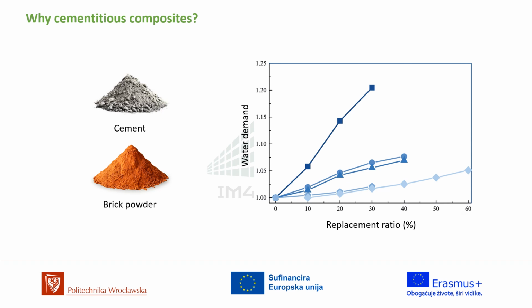Starting with cement. Of course, each of these materials can be replaced. However, incorporating recycled ceramic introduces specific physical challenges that must be carefully managed. As you can see from our experimental data gathered from the literature, crushed brick has a porous structure which significantly increases the water absorption, or water demand, of the fresh concrete mix. Connected with the water-to-cement ratio, it can be observed from the literature that the higher the water-to-cement ratio is, the lower the compressive strength. So in order to deal with that, very often we use superplasticizers to reduce this water-to-cement ratio. However, it's not always good in terms of sustainability.